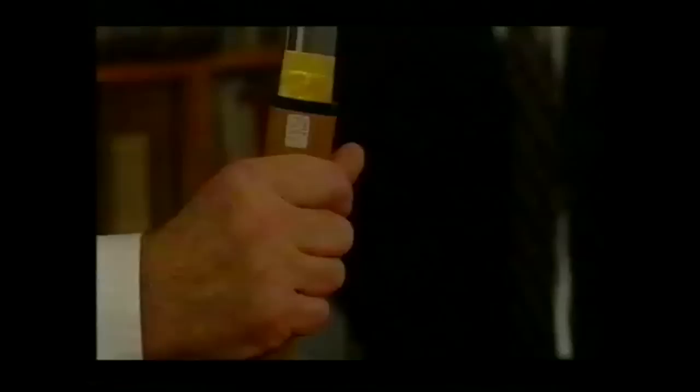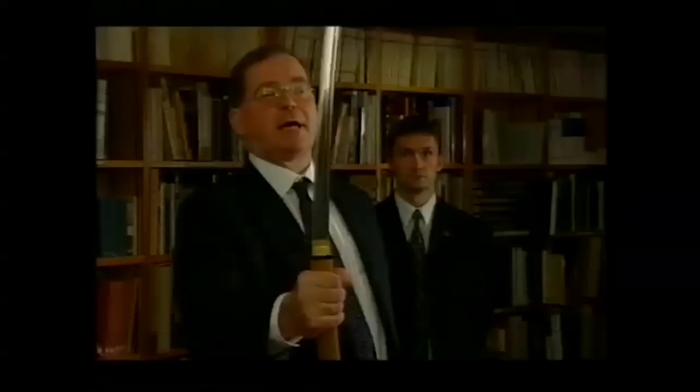It's made by a very sophisticated technology of repeatedly folding the steel over and over again. When the blade is finally formed into its sword-like shape, it is coated overall with a layer of clay. That is partially removed along what is to be the cutting edge. The whole is then heated to the colour of the moon in February or August and plunged into a bath of water. When the blade is polished, its intrinsic beauty is visible in the very many varied shades, hues and textures of the crystalline structures along its edge.